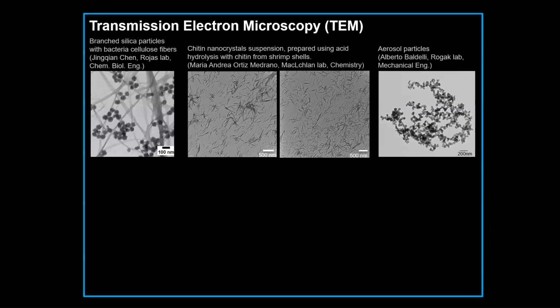So this is the example of the materials samples, the TEM images. Here is branched silica particles with bacterial cellulose fibers. Here is the chitin nanocrystals extracted from shrimp shells. And here is the aerosol particles.